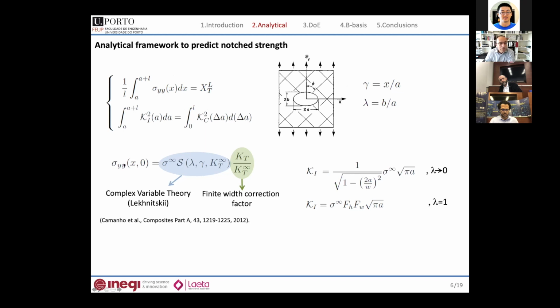And like I said, we don't need the finite elements to solve this because we can get the stress distribution from Lekhnitskii, and we can get the stress intensity factors from closed form solutions that are available in the literature for quasi-isotropic laminates. So we can plug in the stress distribution here in the first equation and the stress intensity factor. Then we have material parameters on the right-hand side of these equations, and we can solve the system for the strength.